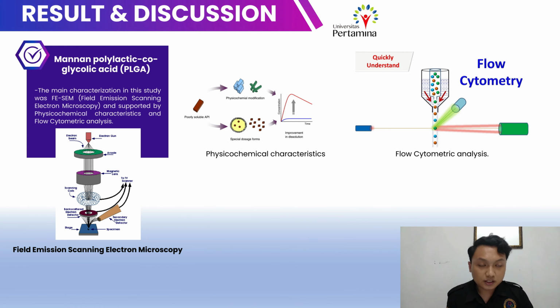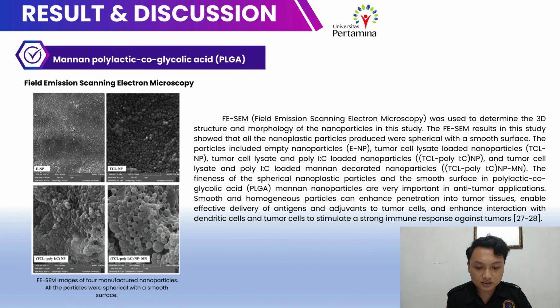FESEM we use to determine the 3D structure and morphology of the nanoparticle. The results show that all nanoparticles, including ENPs, TCL NPs, TCL poly IC NPs, and TCL poly IC MN NPs, are spherical in shape with a smooth surface. The smoothness and homogeneity of these PLGA Mannan particles are important for anti-tumor application as they enhance penetration in tumor tissues, enable effective delivery of antigen and adjuvant, and stimulate a strong immune response against tumor.